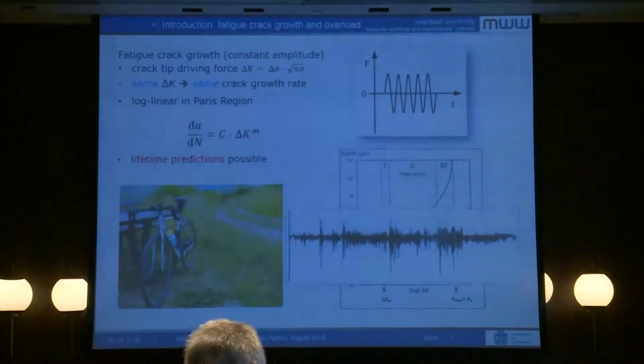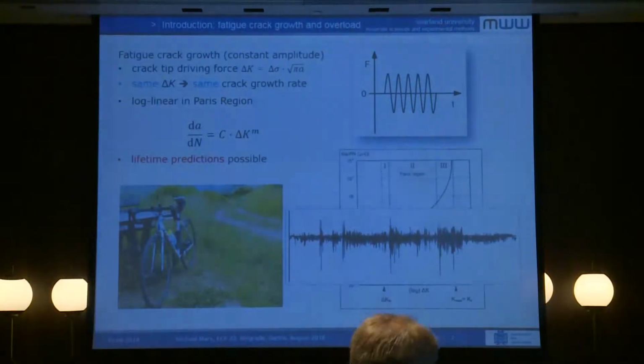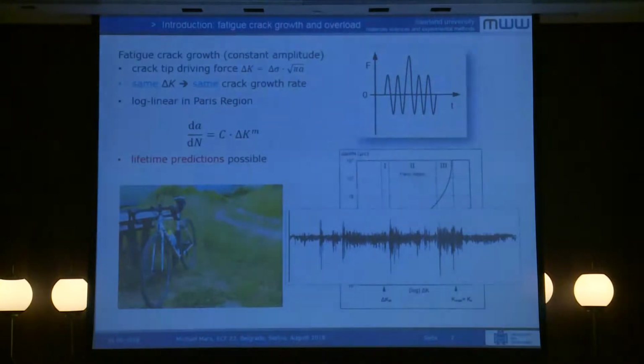Unfortunately, in real life, our loading cycle is not at constant amplitude. It looks more like this. This is a loading cycle during a bike tour of Matthias. And you see there are some heavy loads under compression and tension. And if you want to describe this, it's quite complex. And so we focused first on just one overload cycle during the fatigue.